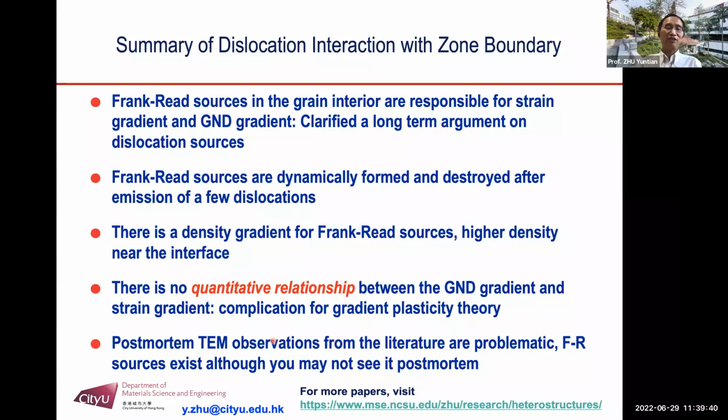This also tells us if you do TEM observation after a tensile test, you will not be able to find these sources. So you have to do an in-situ test. Post-mortem TEM is not enough.